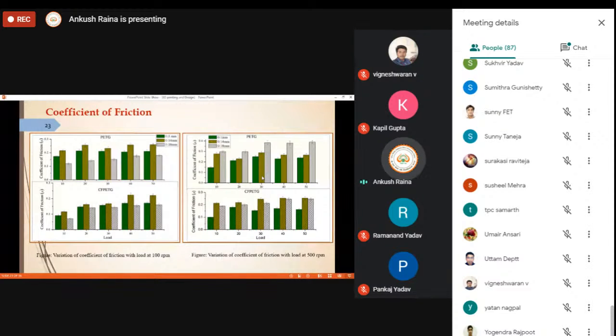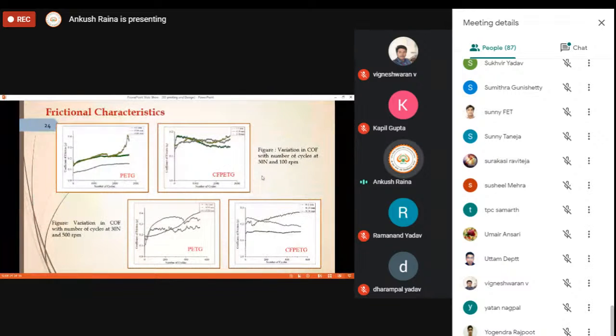So coming towards the frictional characteristics, how the friction is behaving, you can see that the friction behavior has been shown for PETG and CF PETG at 100 RPM and 30 Newton load. So you can here see that for PETG, which is not reinforced with the carbon fiber, there is an increase in the coefficient of friction with the increase in the number of cycles. At the start the coefficient of friction was less, but it is increasing, and certainly there is a sharp peak which can also be observed for a particular layer thickness.